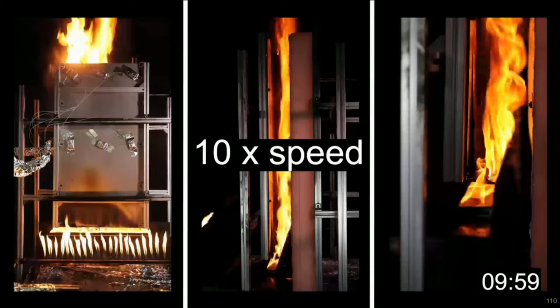It's easier to see once I let it run again, but you can observe that flames are now exiting the top of the ACM panel itself, and that'll be shown at the top left. This will persist until about 10 minutes and 32 seconds, when it appears that the entire inside face of the aluminium sheet facing into the cavity separates from the ACM, thus fully exposing the remaining polyethylene core material.